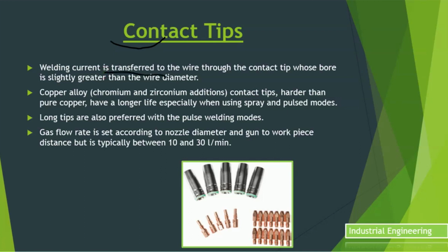The bore of the contact tip is slightly greater than the wire diameter. Contact tip is made up of copper alloy with additions of chromium and zirconium, which make it harder than the pure copper. This makes the life of contact tip longer, especially when using spray and pulse mode. Modes of transfer is again a big topic, which I will explain to you in part 2 of this video. I will upload part 2 very soon.